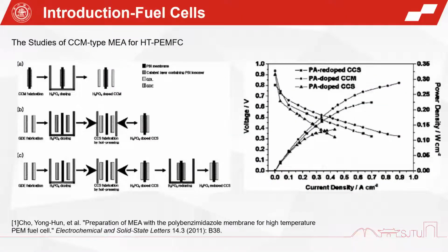Nonetheless, there are still a few studies attempting to develop CCM type MEA for high temperature PEMFC. First, Cho reported a CCM method of pre-coating the catalyst on a dried PBI membrane followed by soaking in PA, and the prepared CCM type MEA had a 13% increase in peak power density compared to the MEA prepared by the CCS method. However, this CCM method also has its limitations. The MEA entirely immersed in PA will cause excess PA to clog the pores of the GDL, increasing mass transfer losses.